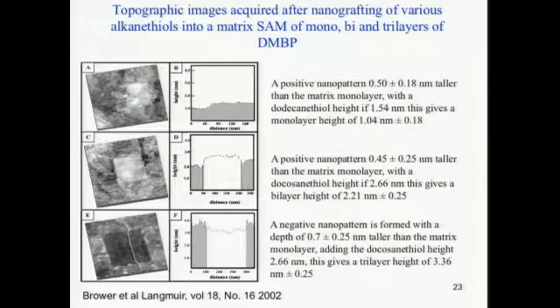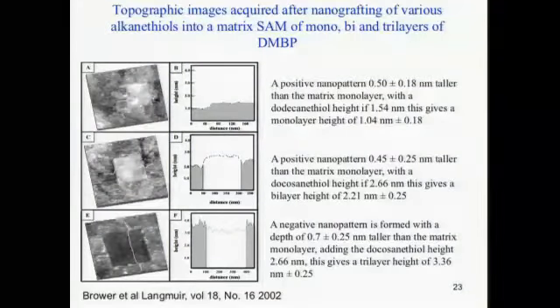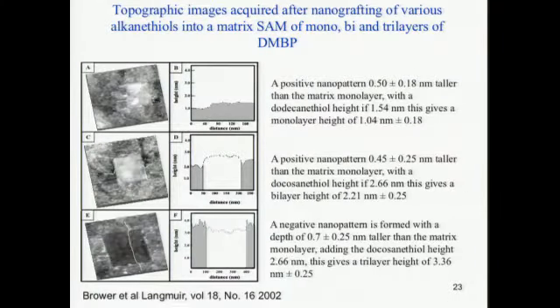And then using techniques like nanografting, where you come in with a different molecule whose size you know, you either make a hole in the layer that you're looking at and then backfill it with the layer that you know the size of, or vice versa. Then you look at the relative height between the molecule that you know versus the molecule you're trying to investigate. You can use that as another backup to proving that you have the number of layers that you want. And these techniques were fairly new at the time, and they actually came into play later, and I'll show you that.